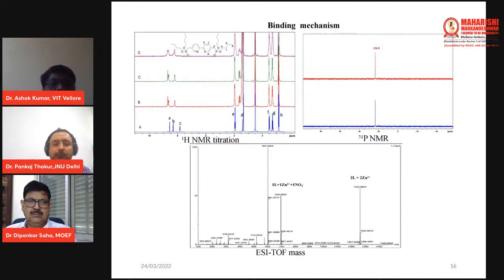There is a change in the proton variations, but in the case of phosphorus NMR, these phosphorus peaks remain the same. It means that zinc is not binding through the phosphoryl group. Zinc is only binding through the pyridyl nitrogen. In pyridyl, there are two nitrogens, and only those two nitrogens are interacting with the zinc.